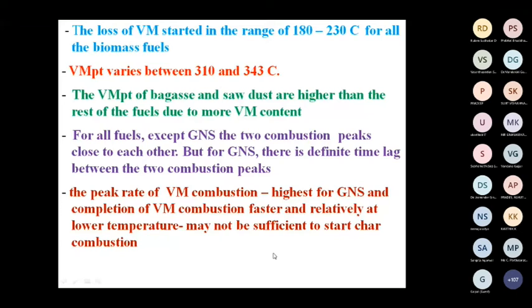So the loss of VM started in the range of 180 to 230 for all the biomass fuels that we have seen. That is volatile matter combustion initiation. The peak temperature of volatile matter is between 310 and 343 degrees. The volatile matter peak temperatures for bagasse and sawdust are higher than those of the other fuels due to more VM content. For all fuels except groundnut shell, the two combustion peaks are close to each other. For groundnut shell, there is a time lag between the two.